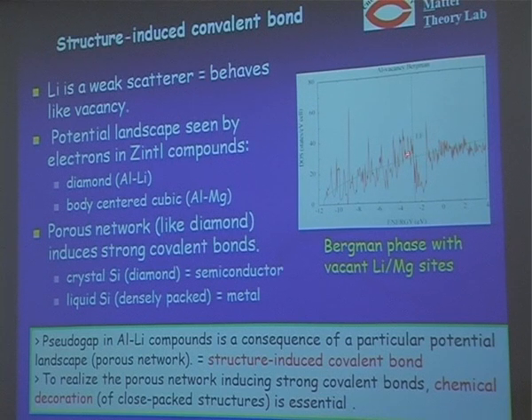Here it is even deeper, or more remarkable, than the aluminum-lithium case. So if the electron sees only the potential landscape made up from the aluminum substructures, very strong covalent bonding will be induced. So the pseudogap in the aluminum-lithium compound is a consequence of a particular potential landscape, a porous network in this case. So we call it a structure-induced covalent bond. And to realize the porous network inducing the strong covalent bond, in this case, the chemical decoration of the close-packed structure is very essential.